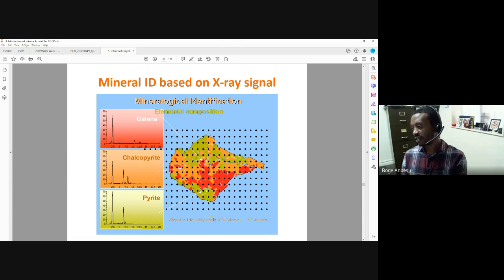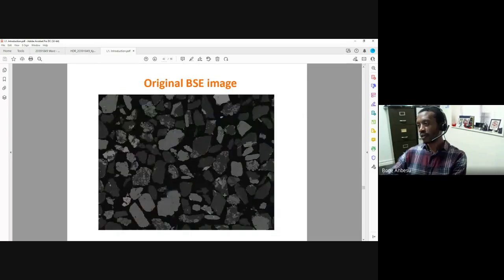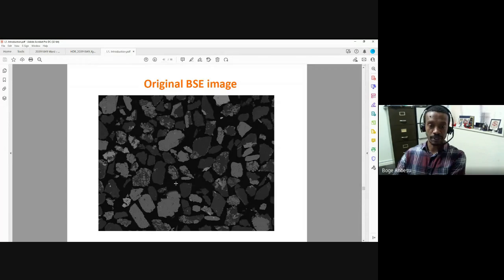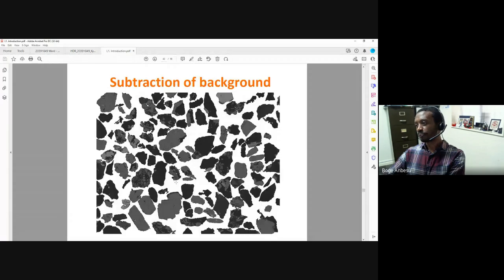Maybe if I grind to 50 or 25, I may have some luck in separating them out or breaking them apart from each other. I liberate them. Then I can think about what grinding mill I'm going to buy to be able to do this. Am I going to do ultra fine grinding, or regular ball milling, or am I going to get away with a SAG mill? All those will come into effect just based on the grain size that we're looking at here. So that will be one input into our combination circuit design, as we said earlier. Also, in this case, most of them are sulfides, so it looks like flotation is a good way to approach this problem.